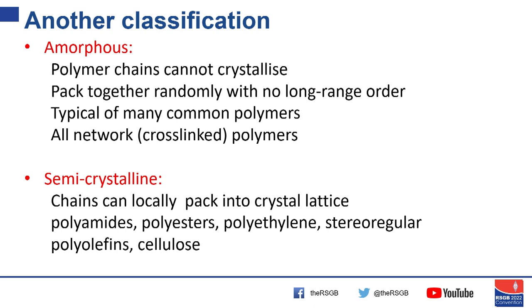There is a small number of molecules where the chain structure is very symmetrical, very linear. Very few bumps on it. And they can pack into a crystal lattice. They can pack to form crystals. So we refer to these as semi-crystalline polymers. And I'll talk a bit more about those in just a minute. But you'll see the names there, polyamides, polyesters, polythene, cellulose. Although there aren't many polymers that will crystallize, they tend to be the ones that we find most useful. And I'll show you why in just a minute or two.